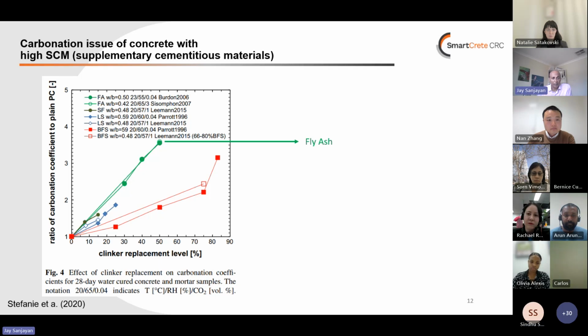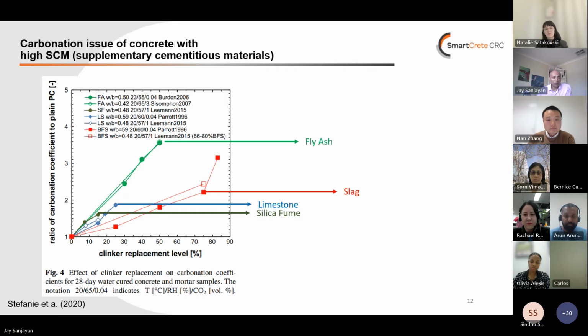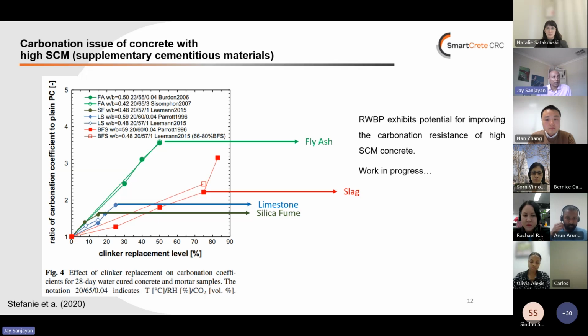increases very significantly. The next one in line is silica fume, and then the limestone, and then slag is perhaps one of the best performing, but it's still 2-3 times higher carbonation when we add supplementary cementitious materials to concrete. So that is one of the reasons that we cannot increase the supplementary cementitious material beyond a certain low proportion. One of the issues is carbonation. So maybe we can use paint in the concrete to increase the carbonation resistance. So that might be a good value add proposition for the reclaimed paint.